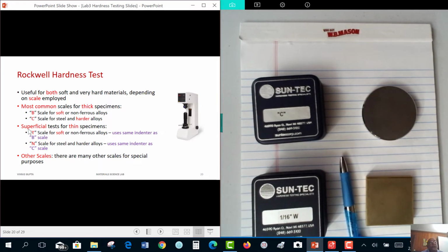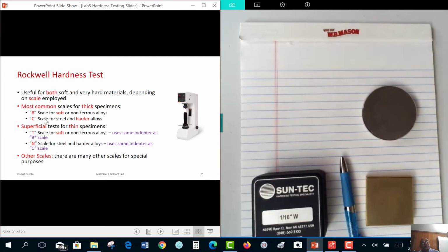Now, there is also what is called the superficial Rockwell hardness test for thin specimens. In case of metals, instead of B scale, we use T scale for soft non-ferrous alloys, with the same indenter as we use for B scale. And then we use N scale for steel and harder alloys, with the same indenter as for C scale. So this is what the indenters look like.